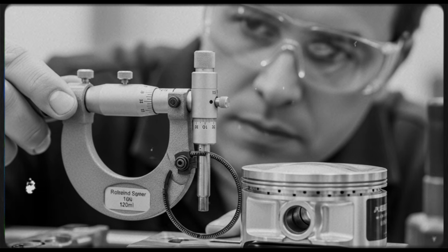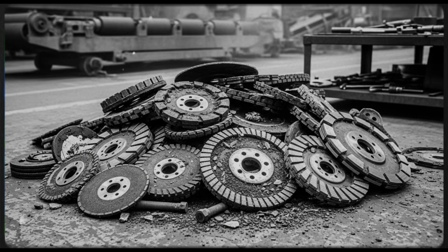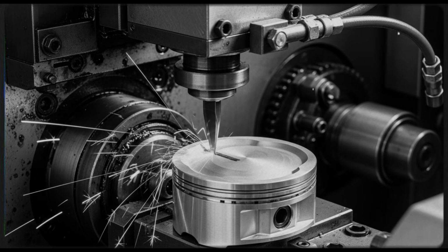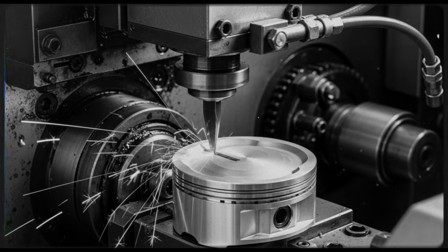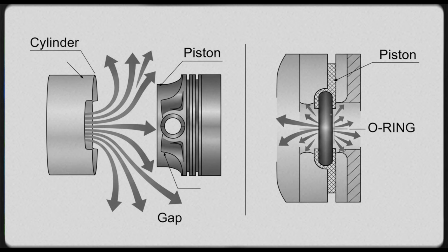The production line became a masterclass in precision and velocity. Each ring began as a coil of high-grade spring steel. The steel was unspooled and sheared into strips, which were then formed into circles. These circles underwent a precise heat treatment process to give them the correct amount of tension. Too soft and the ring wouldn't form a tight seal. Too hard and it would become brittle and shatter under pressure. This heat treatment had to be perfect. A deviation of just 5 degrees could mean the difference between a ring that lasted 300 hours and one that failed in 20.